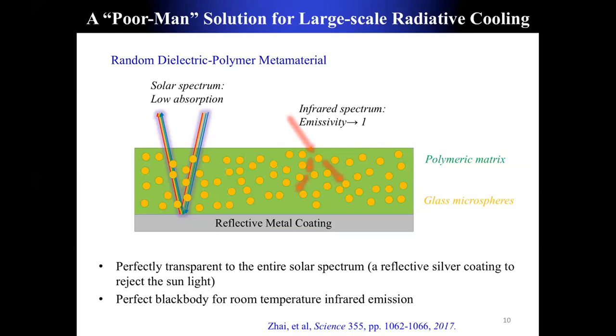This polymer matrix has to be transparent to the solar light, okay? And has to be reasonably emissive, okay? But most polymers are emissive in terms of infrared light. Now, the other thing is that inside this, we use glass microspheres. And the light resonance of the glass microspheres essentially gives us very large emissivity for the atmospheric window, for 8 to 13 micron. In other words, this material has two pieces.